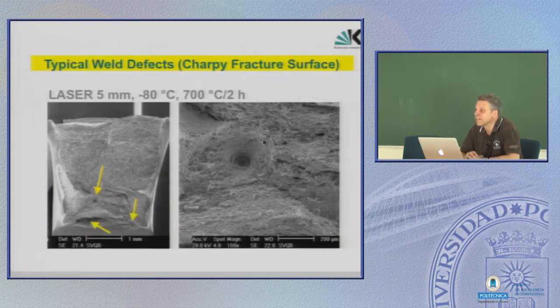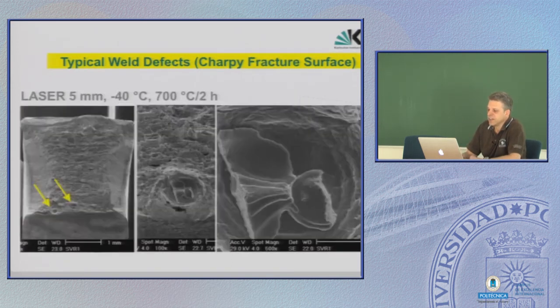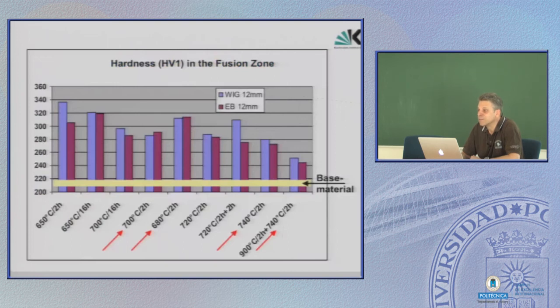Beautifully shaped crater-like crack pictures, but things you don't really want to have. Also here in laser seems to be also some precipitates shaping during the melting. And well, in general, if you melt material and quench it down, that's not the best process for any material, also for Eurofer. Here is a very broad overview on many different kinds of heat treatments.